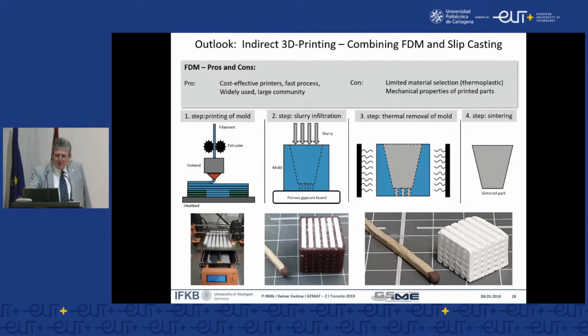You see the intermediate product, the yellow-brownish is the polymer form, and right hand down, that is the final sintered product. It is not so different from the printed materials I showed you before, but the nice side effect was, it's more a secret, that this machine system did just cost 12,000 euros. That was a tenth of the original printing machine. So even with very economic means, you have access to such interesting material.